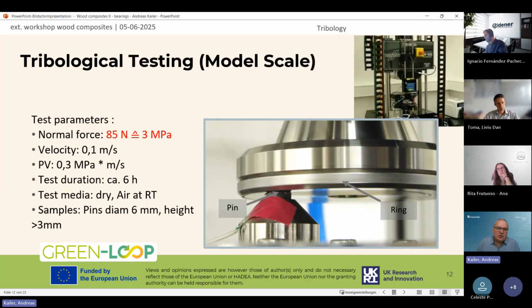What we did for tribological evaluation is shown here as a testing method. We used at first a pin-on-disc geometry. We used wood composites as pins, and we purchased rings from bearing manufacturers. So this was the opportunity to buy with a rather small budget a large number of such rings, and so we were very efficient and could conduct a large number of tests with this type of tests.